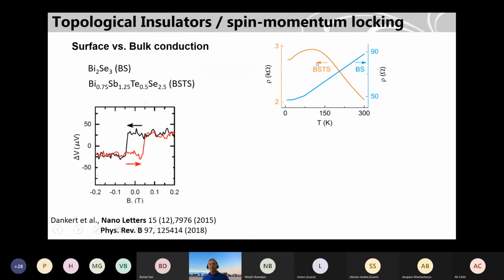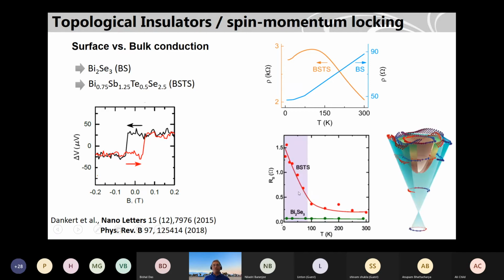And above that, bulk contribution can also be there. And we measured such signals in both devices. And now we plot the magnitude of the signal with temperature. So what we see in the bismuth selenide is that it's almost flat with temperature. But for the BSTS, the magnitude of the signal goes up below 100 Kelvin, where surface states are dominating.